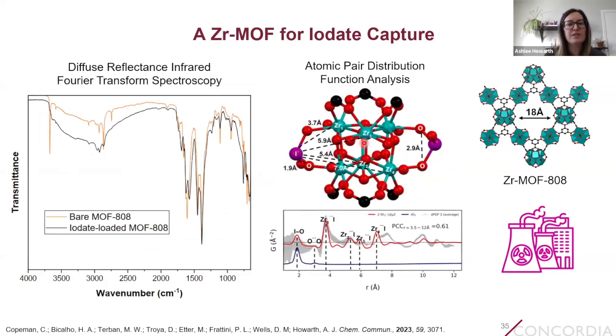We can also use different techniques to try to understand how those iodate oxyanions are interacting with our MOF. So diffuse reflectance infrared Fourier transform spectroscopy shows us that in the bare MOF without iodate, we have a very sharp band around 3,700 wave numbers corresponding to terminal hydroxyl ligands on the zirconium-based node. And after adsorption of iodate, we see that that peak decreases significantly, giving us insight that those iodate oxyanions may be replacing those terminal and labile hydroxyl ligands on the node of the MOF.